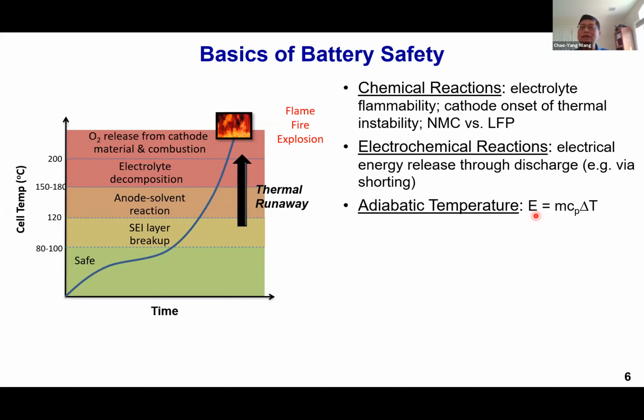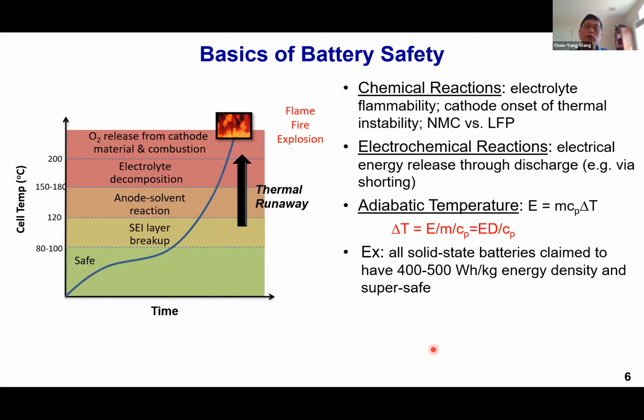So that makes E equal to... okay, I think I need to go really fast, right? So that makes the electric energy equal to m C_p delta T, which gives you the maximum temperature rise after all the electric energy is released. If you do a simple manipulation, that is energy density divided by C_p. So let's do a very quick example.